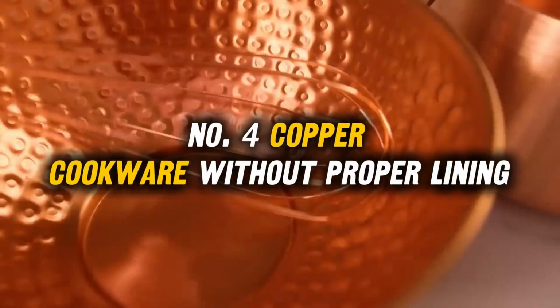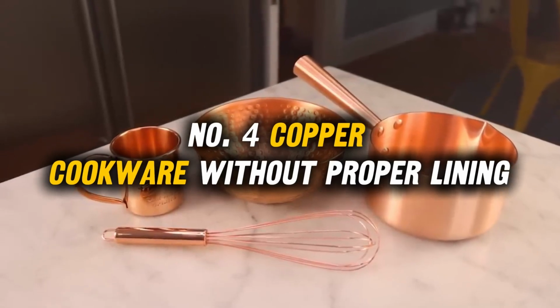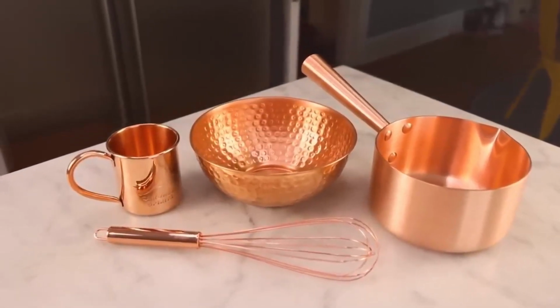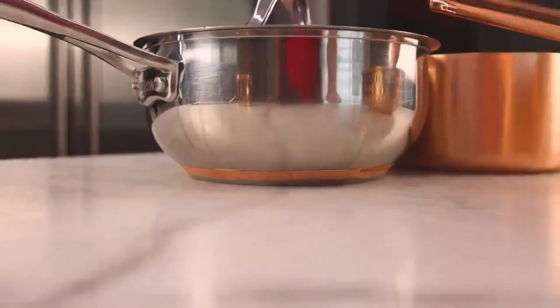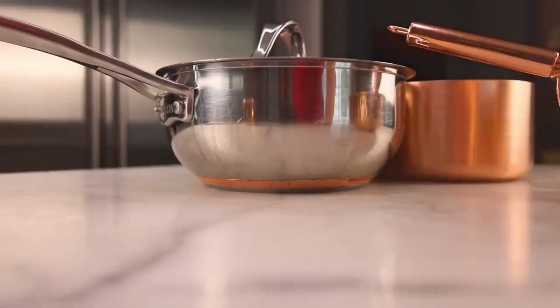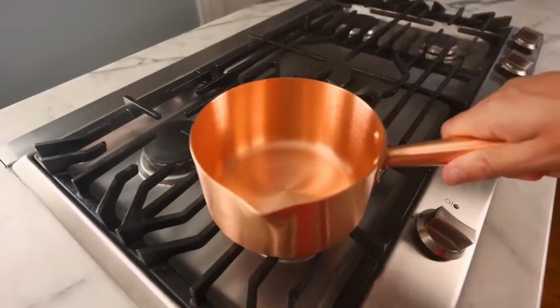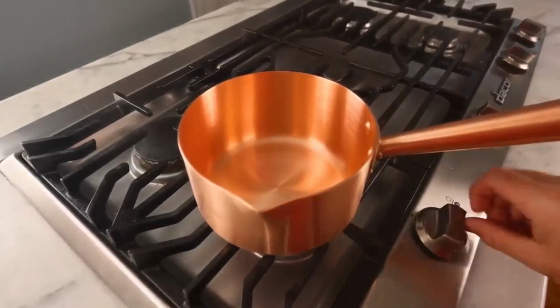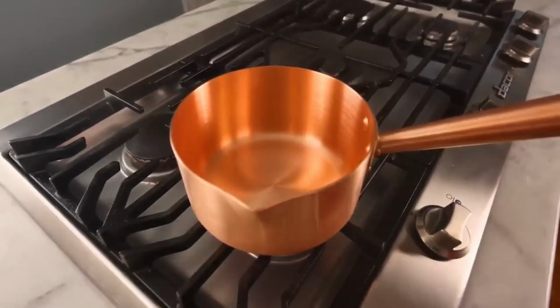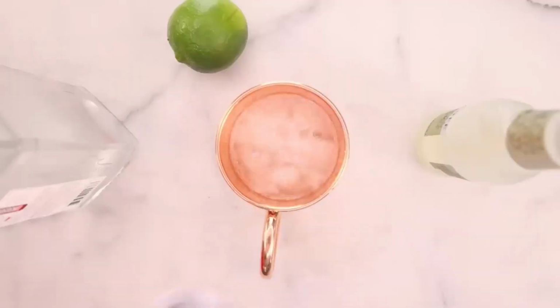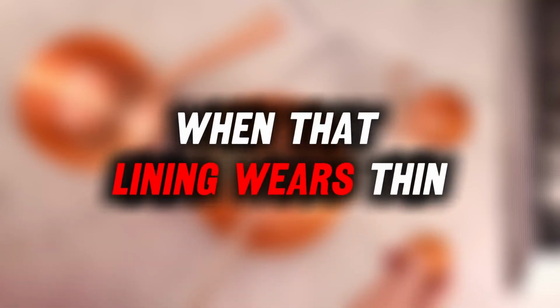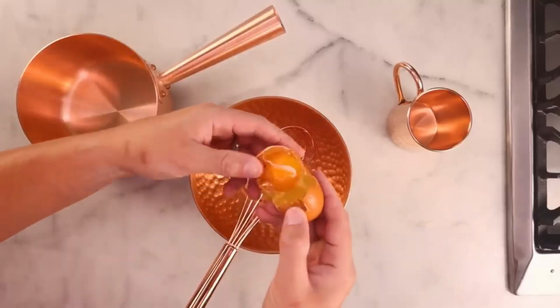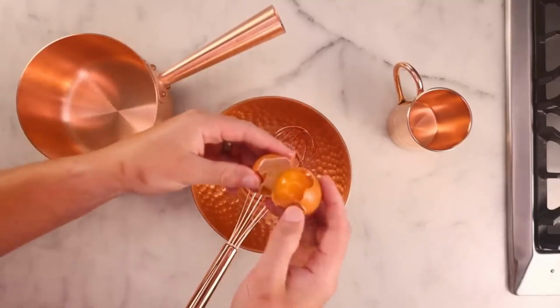Number 4. Copper cookware without proper lining. Copper looks pro and cooks fast and even. But without a safe lining, the metal meets your food and reacts. Here's the truth. Acid and salt pull copper ions into sauces, stocks, and jams. Long, slow, acidic cooks pull more. Classic copper has a lining, soft tin or bonded stainless, to block contact. When that lining wears thin, scratches, or melts off spots, copper shows through.